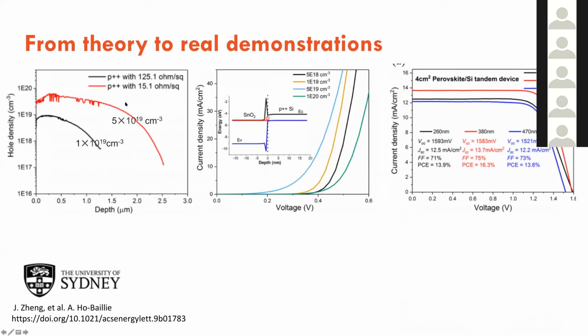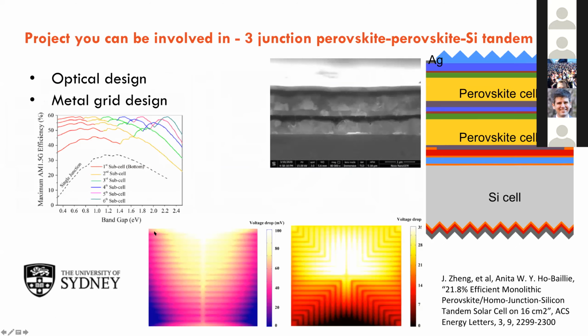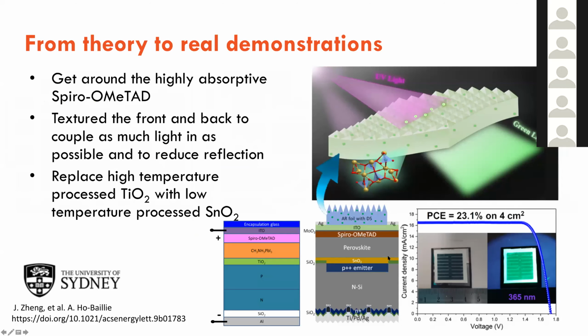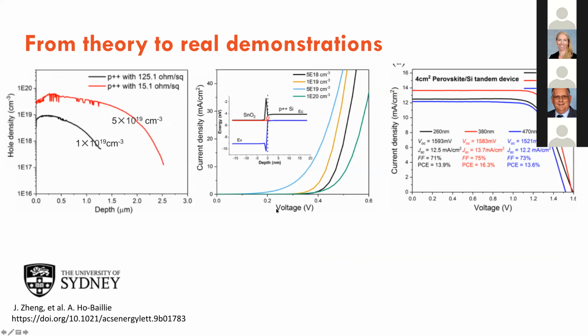For example, we have to make sure the doping of the P material, I'll just go back, of the P material here is optimized so that it will do a good job of separating an electron and holes and get the electrons to go up, the holes to go up and electrons to go down. Also, the tin oxide interface is very tricky. We want it really thin to make it deposit onto the silicon cell. We've got to make sure the silicon cell is wettable, and that means we will have a little bit of silicon dioxide on the cell, and then we worry about the barrier created by the silicon dioxide.